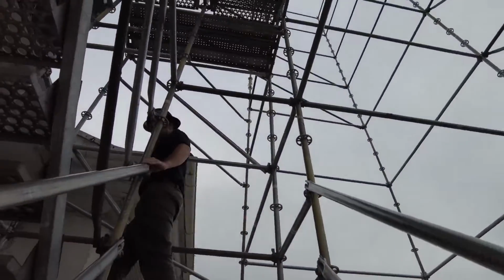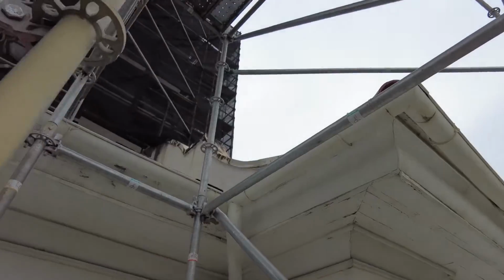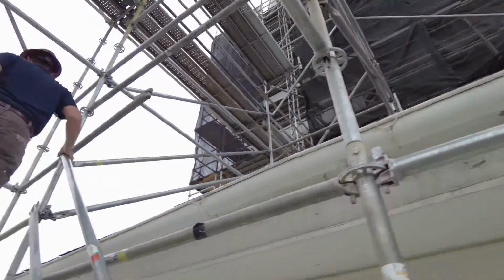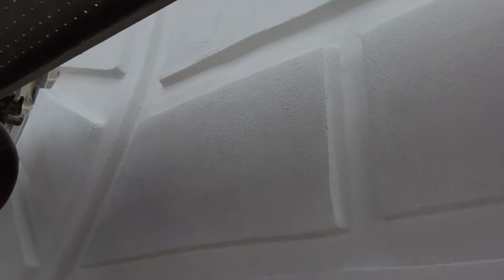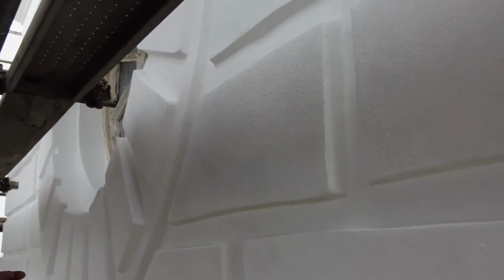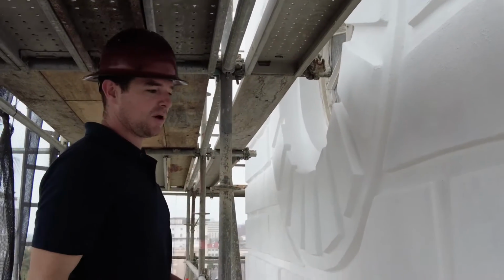The bell tower masonry took in moisture over the years, and the elastomeric paint, effectively a plastic coating, kept the moisture from being able to evaporate. That held moisture likely exacerbated the rusting of the embedded steel rods in recent decades. There was steel running down through this section. The steel had rusted and pushed a section of the wall out.